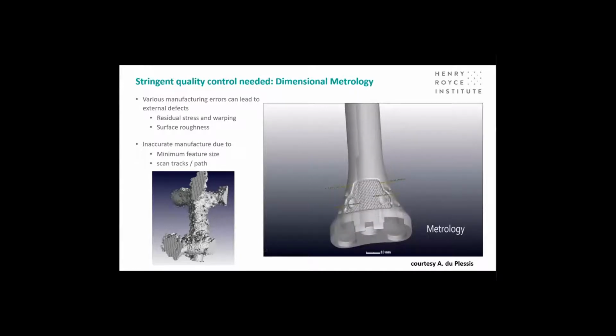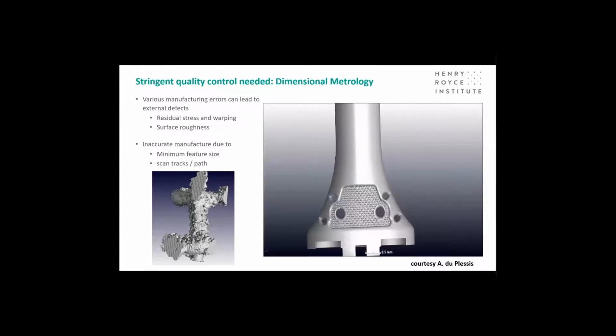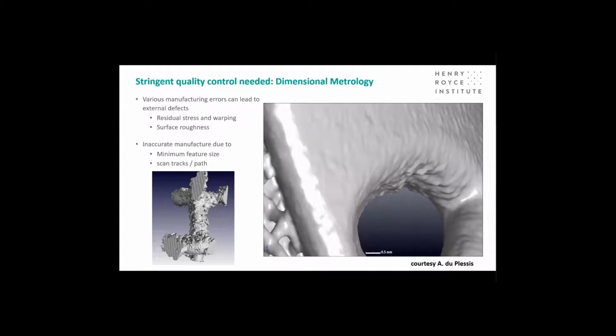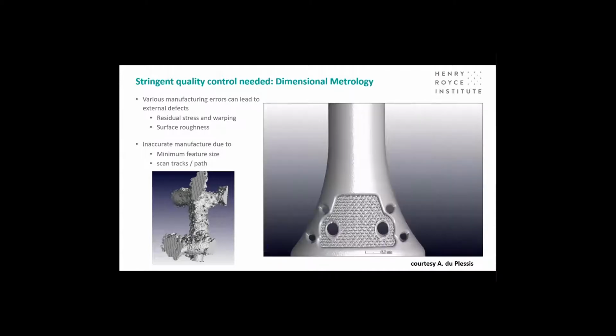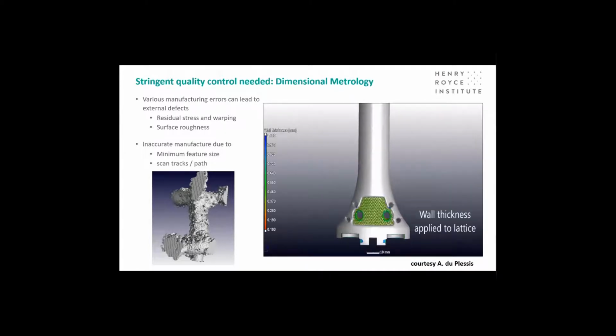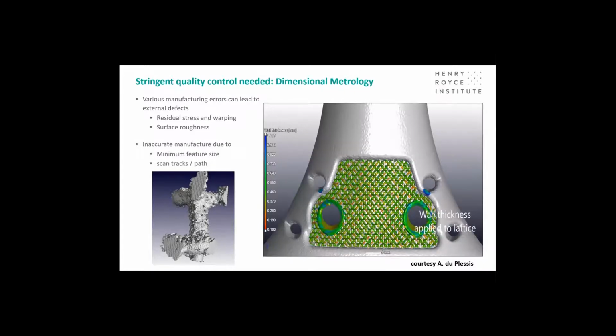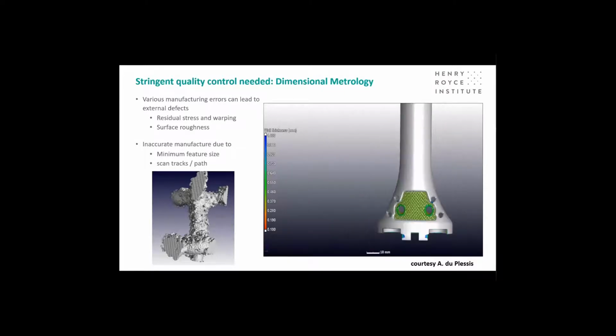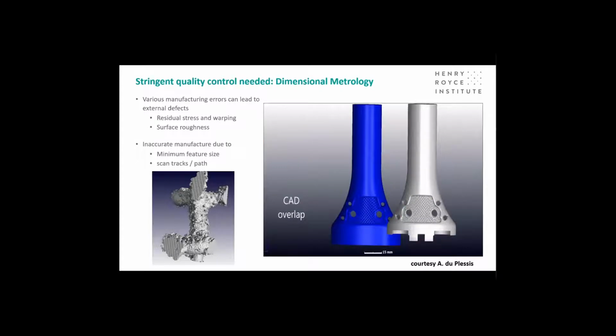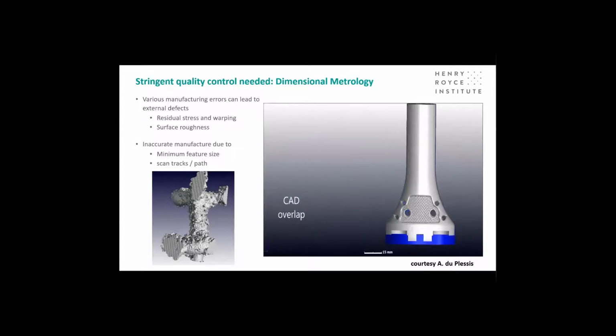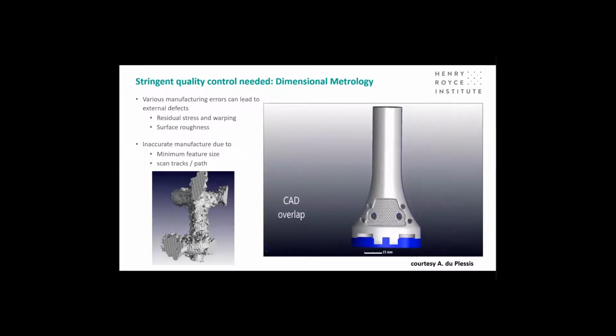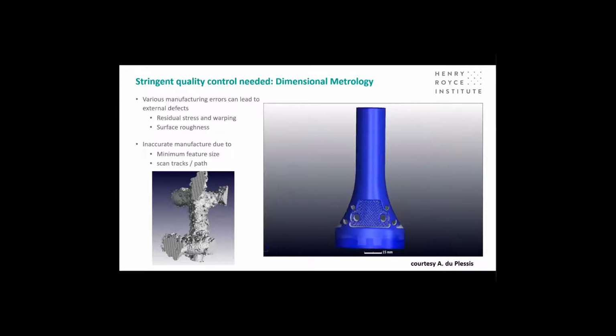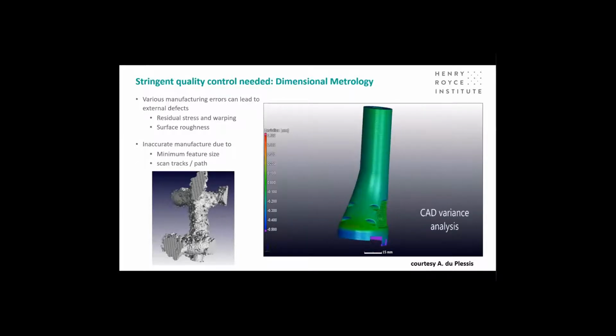The image on the left shows the kind of defects that you often see when you make lattices. You can see adhered particles on the surface. You can see a sort of knobbly structure due to the definition of the additive manufacturing process. And you can quantify that accurately by 3D X-ray CT, just like you could with a coordinate measurement machine.